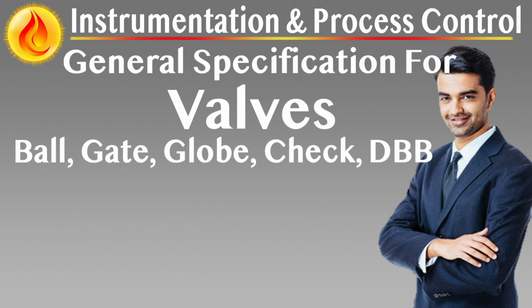All valves used for shutoff in hydrocarbon services must achieve tight shutoff performance to leakage rate Class 6 per ANSI FCI 70-2 or its equivalent. Seat leakage testing must be conducted under both ambient and high-temperature conditions. For high-pressure throttling service, butterfly valves must demonstrate stable control characteristics and be suitable for modulating duty where specified in the data sheets.